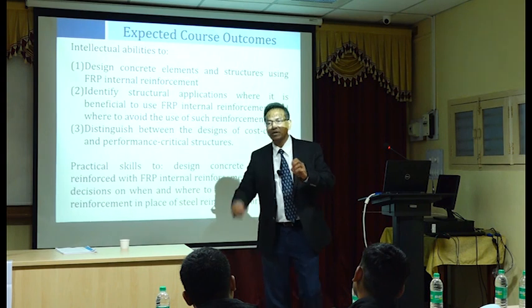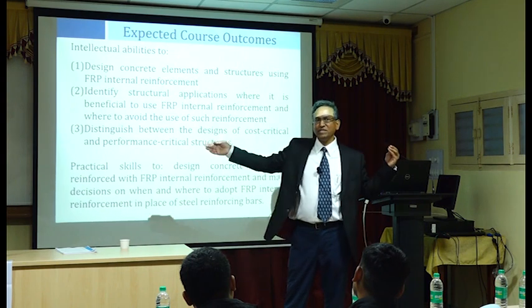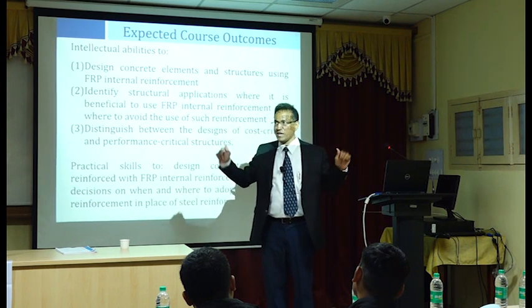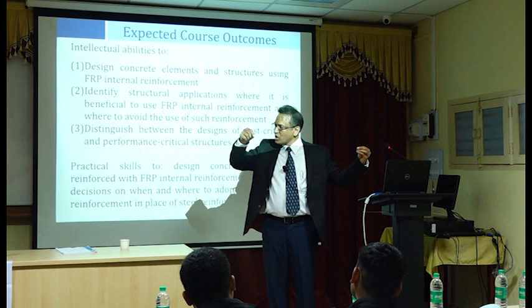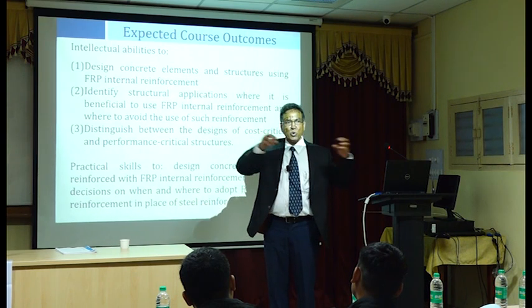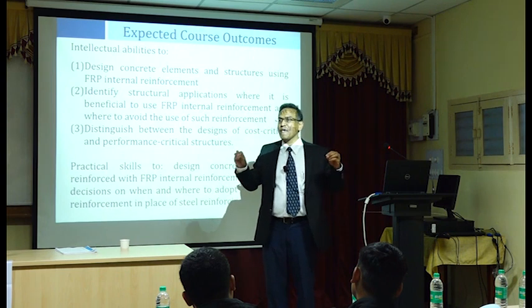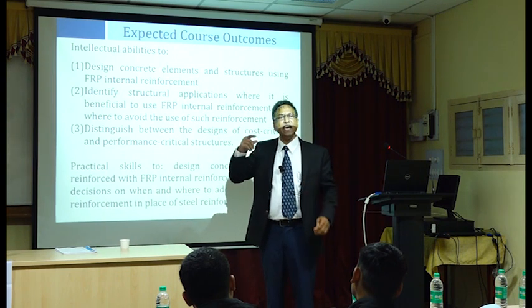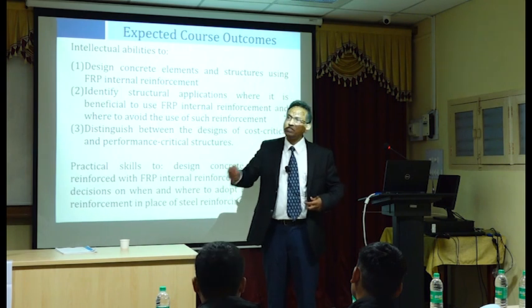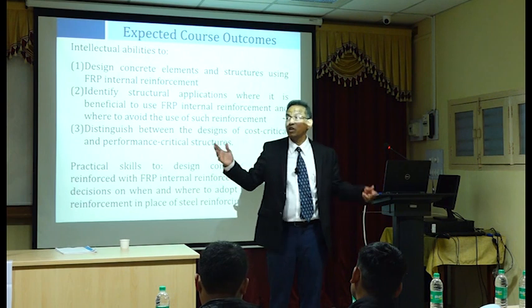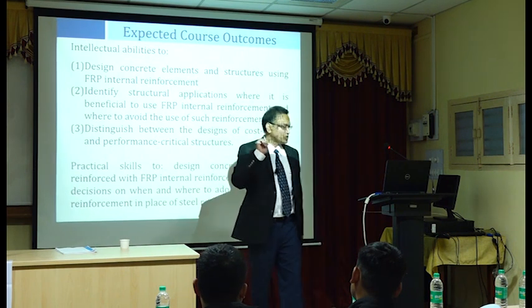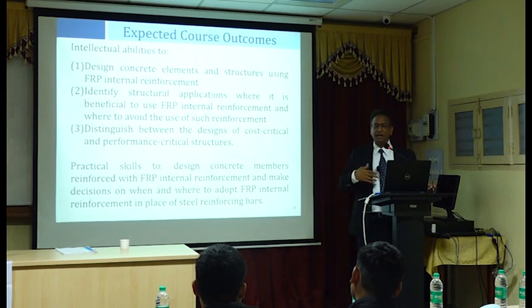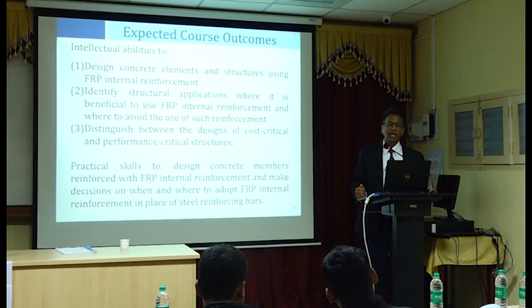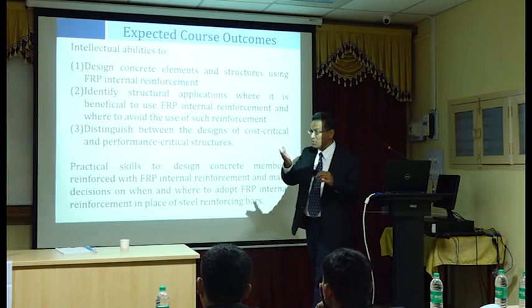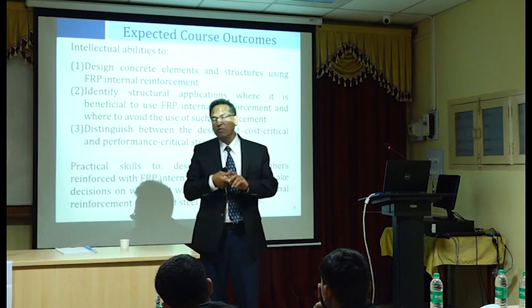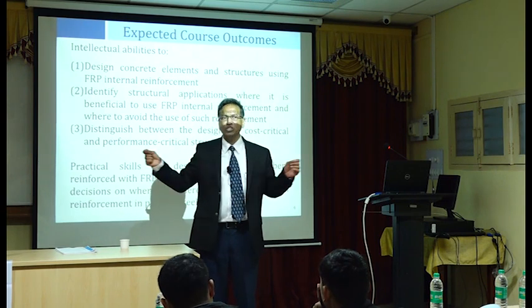You know why? Because if you have a steel bar, no coatings, that will have some amount of corrosion, fine. But if you have an epoxy coated bar, you have a small, localized damage at different locations, that will cause very accelerated corrosion. In fact, it's worse than the reinforcing bars without any coating. It's a big thing, okay? So don't assume that epoxy coated bars are the best and they can solve all our problems. Maybe not as much. There are a lot of problems with epoxy coated bars, just like you mentioned. Bond is a big problem. Of course, we adjust that by adding a 10-15% additional development length.